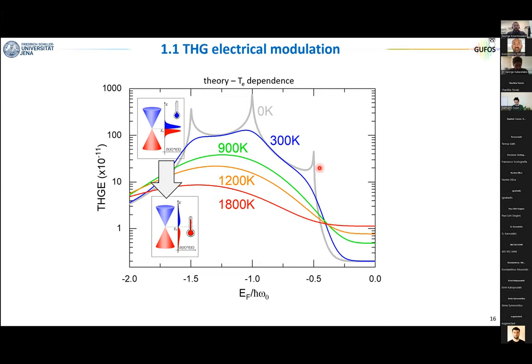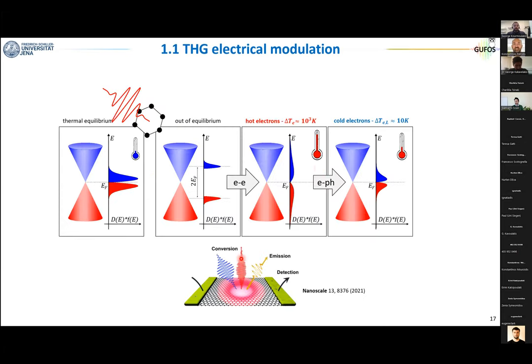And to understand why this is so relevant in nonlinear optics, we should also understand what hot electrons are and how they evolve. Now imagine that initially you have graphene at equilibrium, then you arrive with a very short pulse that breaks this equilibrium. And at the very beginning, the system will be in a so-called out-of-equilibrium condition. That means you have delta Dirac distributions in the upper and lower cone. This cannot be described by the Fermi-Dirac distribution.